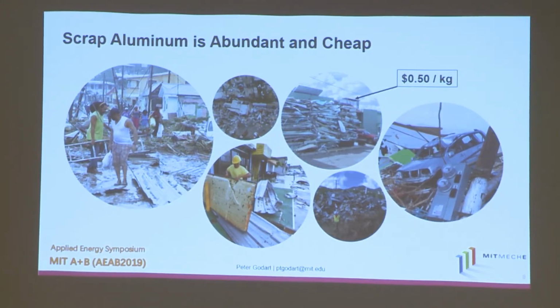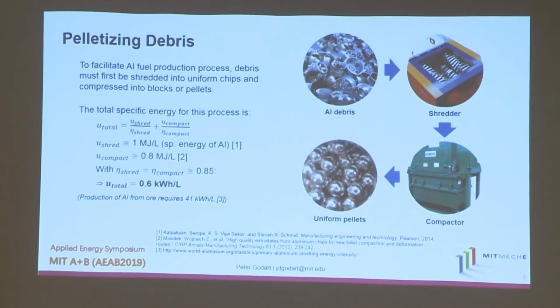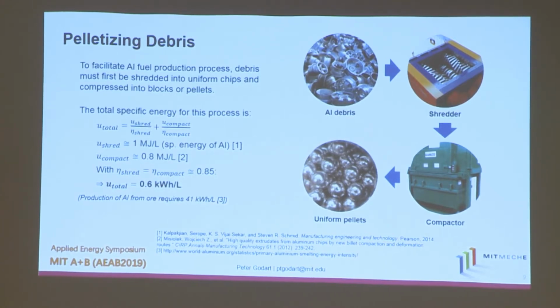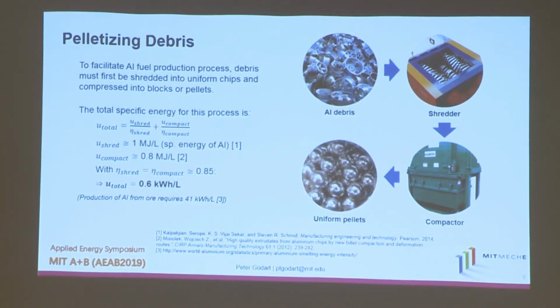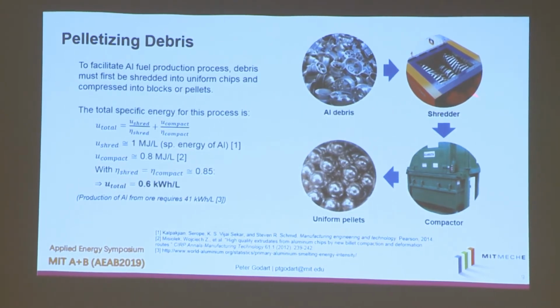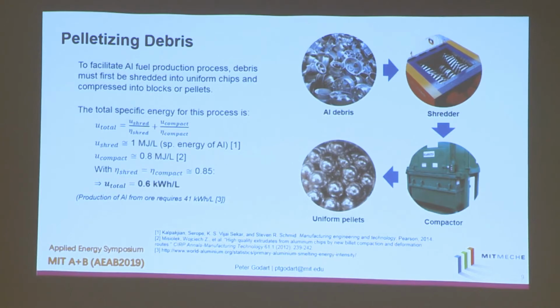And I should mention here that in places like Puerto Rico and the Dominican Republic, which are highly susceptible to these natural disasters, aluminum is about 50 cents a kilogram for scrap. And so, of course, there's no free lunch here either. You would take aluminum in some arbitrary geometry, and you'd probably want to break that down into smaller pieces. And so just a quick back-of-the-envelope calculation to determine how much energy is required to shred and then compact aluminum into uniform pellets. That's only about half a kilowatt hour per liter. So again, compared to that 23 kilowatt hours per liter that I mentioned earlier is embodied in that aluminum, this is pretty much negligible.